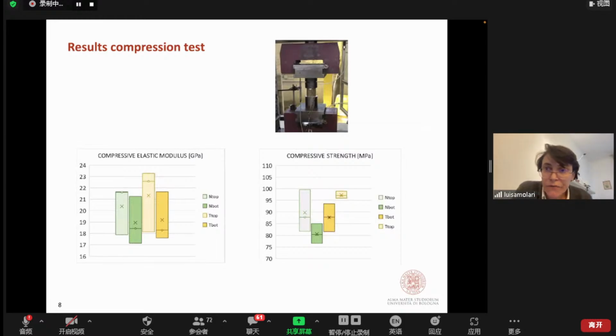So the results for the compression test. What we saw is that for the compressive elastic modulus, actually we do not see a lot of difference here. In green, the untreated culm, in yellow the treated ones, and in light color the parts that are from the top, from 2.5 meters to 3.5 meters, and in the darker color the ones that are on the bottom part of the culm. So what we can see is that basically there is no difference in the stiffness.